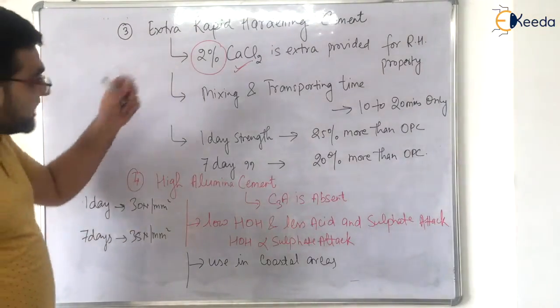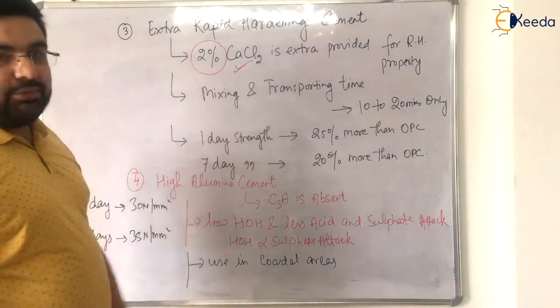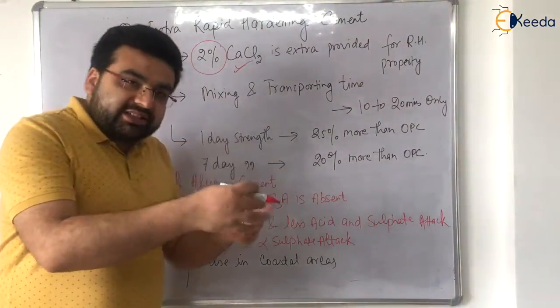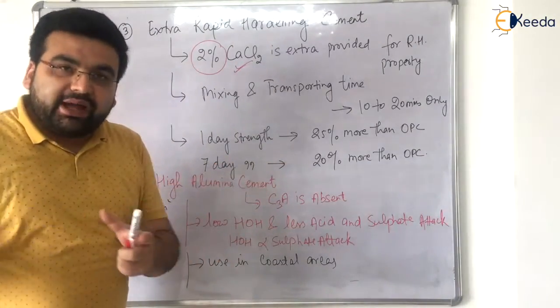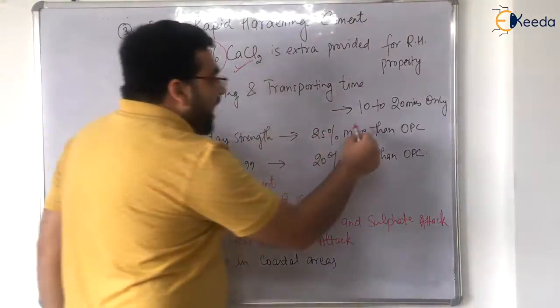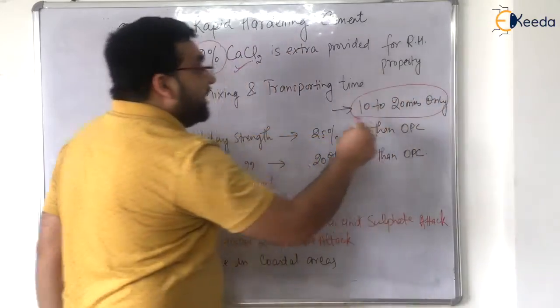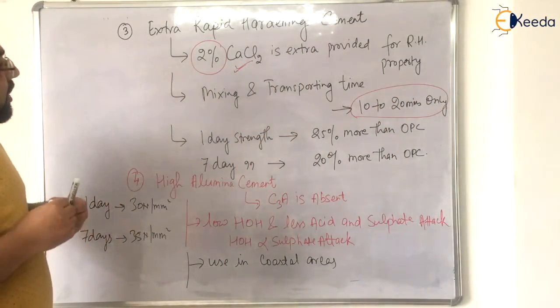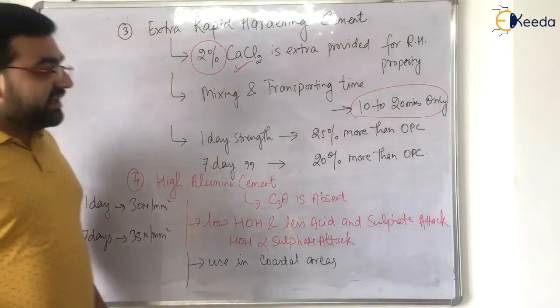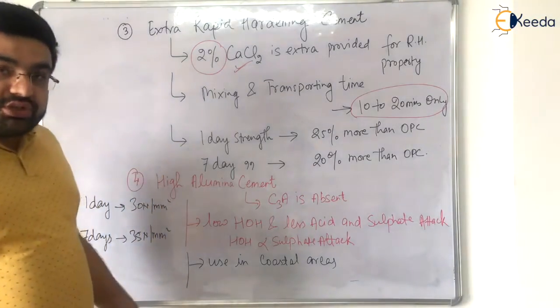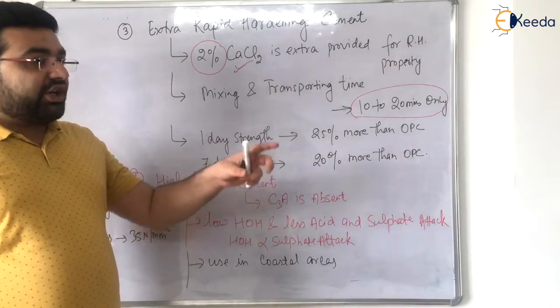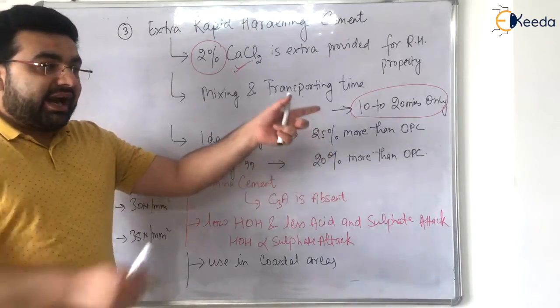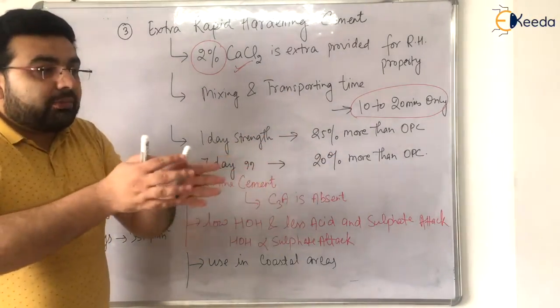Okay. Next property is mixing and transportation time. Now, when you mix and when you transport it in a batch, the total time you have is only 10 to 20 minutes. It means that if you are using rapid hardening cement in a particular region, then the manufacturing of this cement and the site should not be very far.